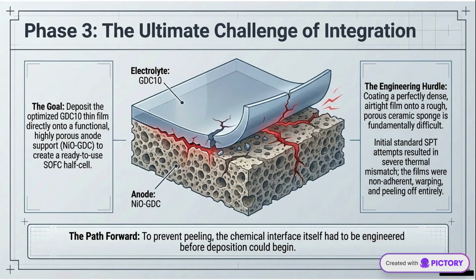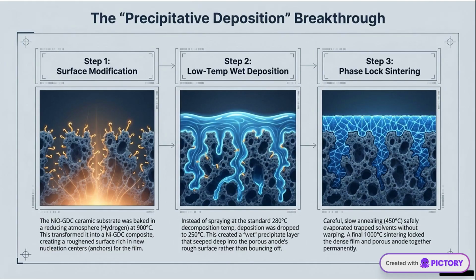Phase 3 tackles the challenge of integrating GDC-10 into functional half cells. By engineering the chemical interface, we prevent peeling and ensure a robust, adherent film. The precipitative deposition method revolutionizes integration by modifying surfaces, enabling low-temp wet deposition, and phase-lock sintering. This ensures a durable and cohesive structure.